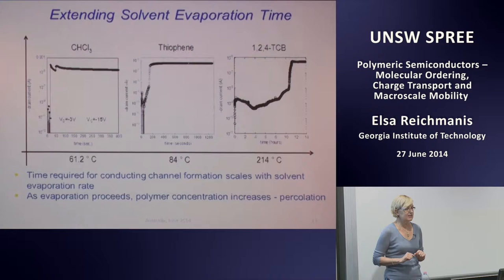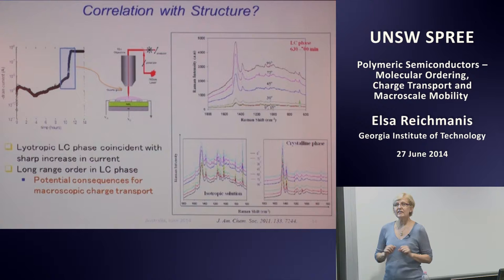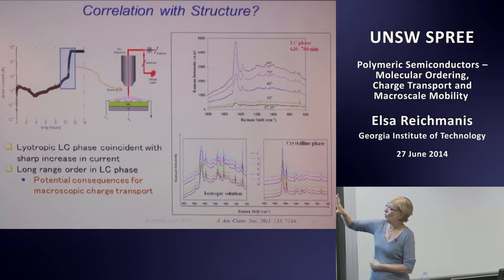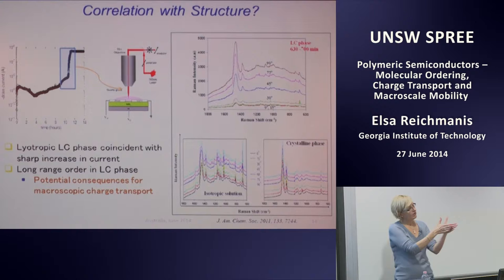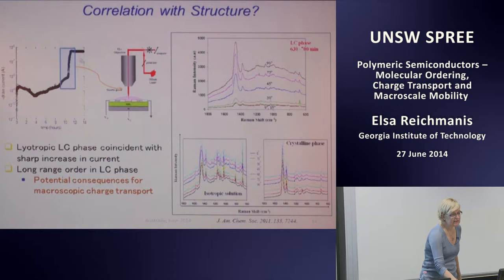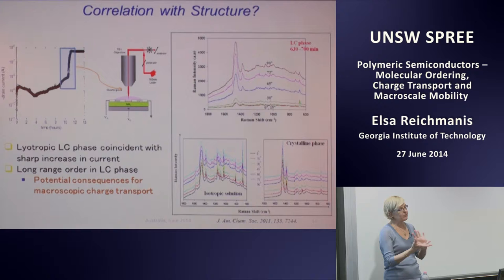With trichlorobenzene, the time frame is long enough that we can now start to spectroscopically interrogate that droplet to see if we can identify changes that are occurring during solvent evaporation. We did this using micro-Raman spectroscopy. And what we find is that if we wait, we see a very sharp rise in drain current roughly 10 to 12 hours after depositing that droplet.